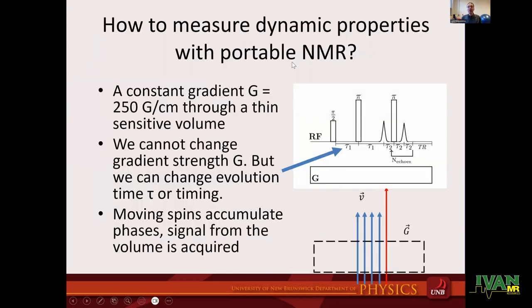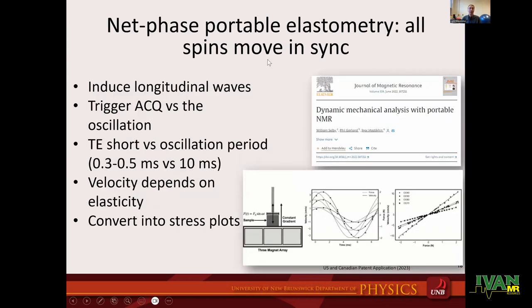So how do we measure these properties with portable NMR? The basic idea is simple. It's a constant gradient, so we cannot change the gradient strength, but we can change the evolution time between our RF pulses, or we can change the timing of our instrument relative to the vibration phase, for example. And the spins will move through the gradient, they accumulate phases, and the signal will be acquired with an RF coil. And when all your spins move in sync, for example, when you have a longitudinal wave through your sample, you can then measure elastic properties right away.